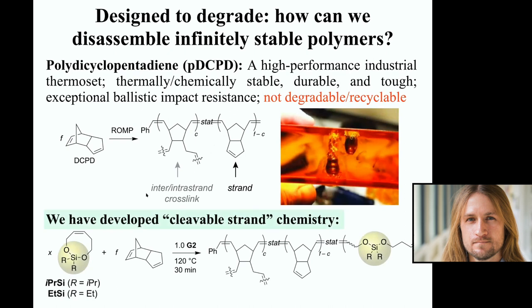So in my laboratory in the last few years, we've developed what we call cleavable strand chemistry, which is an approach that allows us to go in with molecular precision and ask the question, does it matter where we clip bonds in polymer networks in terms of our ability to disassemble them and recycle them? Specifically using this ring-like structure, you've seen many octagonal rings today. This is another one here that we've developed that has this oxygen-silicon-oxygen linkage that we call a bifunctional silyl ether. The remarkable thing about this molecule is when you add it to dicyclopentadiene under ROMP conditions, you generate samples of polydicyclopentadiene that are just like the parent material, but now have these oxygen-silicon-oxygen linkages embedded within their strands.